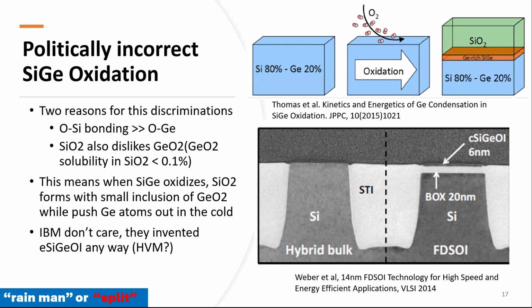And they are difficult to deal with. Here is what happens when you oxidize SiGe. I call it politically incorrect, meaning that it has some prejudice against one or the other. Say you have a SiGe alloy, 80% silicon, 20% germanium, that's typical. People right now use close to 30%. 20% is fine, and you oxidize it. What do you see? They will form SiO2 preferentially, and then you will form a germanium-rich layer here, because germanium cannot go anywhere. Silicon gets some oxygen and oxidizes to become SiO2, and germanium is left behind.